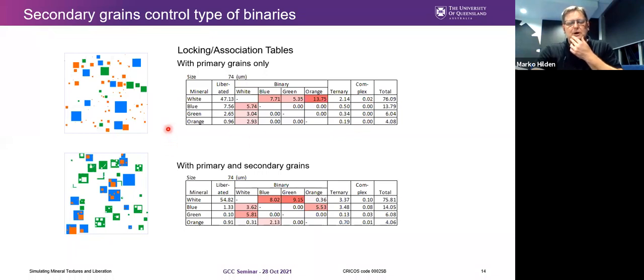And you can see that if you have just primary grains, the type of binaries that you create are just the colors with the matrix mineral. Whereas if you have secondary minerals, you can get binaries between these different colors, and fewer of these others. So the association basically controls the kind of binaries that you produce. And you can imagine that if you took a sample of crushed ore, analyzed it, and created these sort of tables, you can begin to infer the intact structure of the ore just from the particles, basically putting the ore back together again. So I'll talk more about that a bit later.